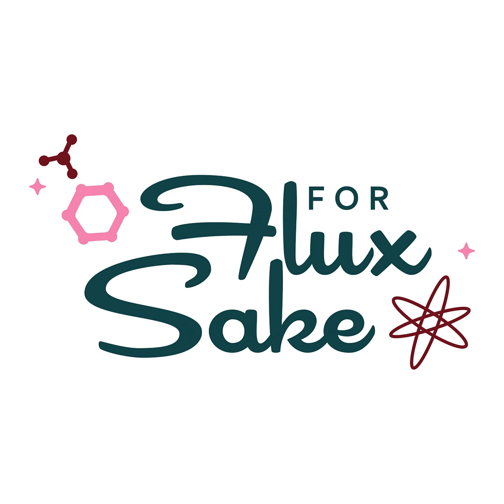Good. Yeah. And the amazing thing is when you do look at these firing curves, what you see is that it's always a curve. And this is where I get my sense of what's really going on with these firing temperatures. And what Teresa's saying is exactly what you see. People often make the assumption that when a clay company lists their firing temperature, they are saying that that's where it's vitrified. And there is no correlation between those things. The clay companies can say whatever they want. People make a connection in their head: oh, it says cone 6 to 5, that means it's vitrified. No, they're just saying that that's the temperature they think you should fire to. They are not trying to meet any particular standard.